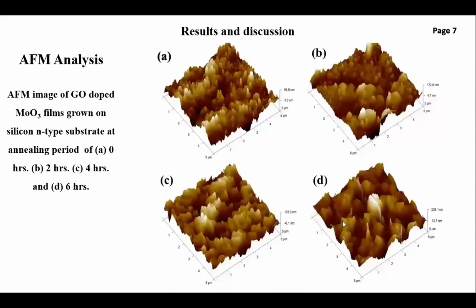Also, the AFM analysis was displayed here. The film thickness for A, which is as deposited, is 94.8 nanometers, and the film thickness increases with increasing annealing period, having the values of 172.6 nanometers and 175.6 nanometers, and lastly 235.1 nanometers, which confirms the effect of the annealing period on the film's AFM properties.